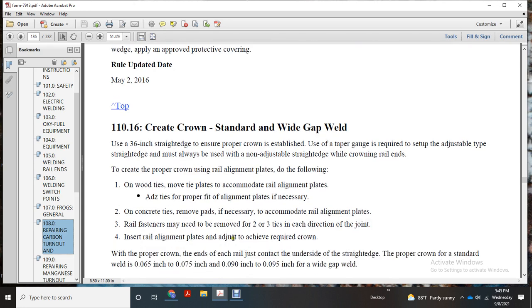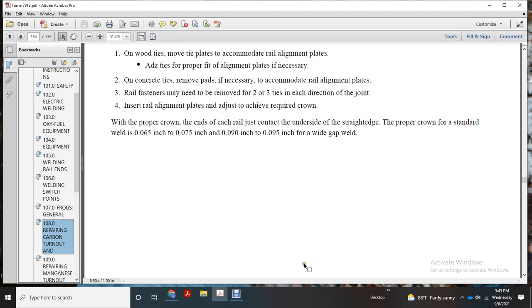Insert rail alignment plates. Adjust to achieve the required crown at the end of the rail. Each rail joint end must contact the underside of the straight edge. Proper crown over the standard weld is 65 thousandths of an inch to 75 thousandths of an inch, or 90 thousandths of an inch to 95 thousandths of an inch for a wide gap weld.